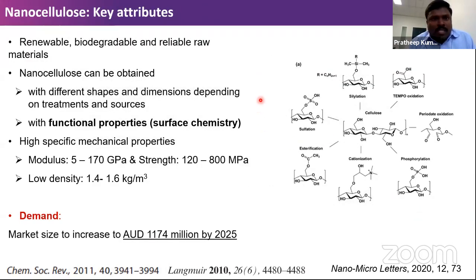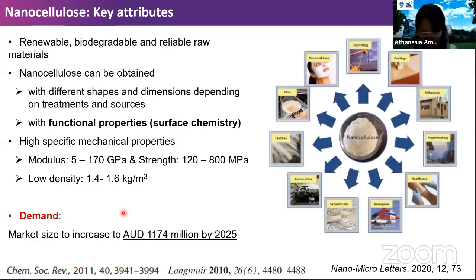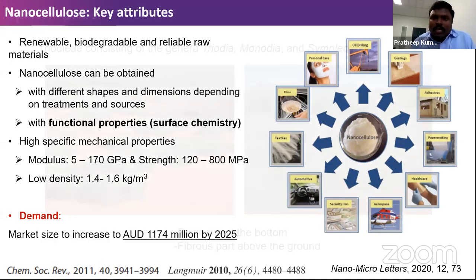And as Amanda mentioned, it's not only about the mechanical filler. It's about the surface chemistry, because the hydroxyl group offers many chemistries that you can do, like acylation or oxidation or phosphorylation. So these functionalities are important when you want to make some other functions, okay? And there is a growing demand for this particular nanocellulose material, and it's going to be used heavily in different applications as well as an additive.